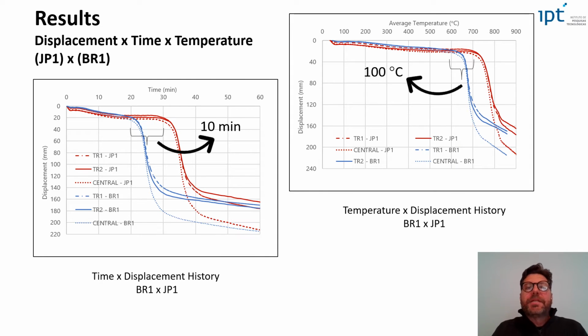This is a time and temperature versus displacement graphic for both JP1 fire-resistant steel, here represented in red, and BR1 conventional steel, here represented in blue. What we can see here is that the plastic deformation, or the limit test condition, occurred 10 minutes later, or 100 Celsius degrees higher, for the fire-resistant steel compared with the conventional steel.